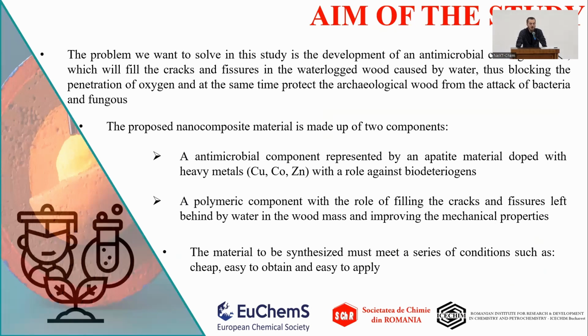In this scope, the problem we want to solve in this study is the development of an antimicrobial material which will fill the cracks and fissures in the waterlogged wood caused by water, thus blocking the penetration of oxygen and at the same time protecting the archaeological wood from the attack of bacteria and fungus. The proposed nanocomposite material is made up of two components: an antimicrobial component represented by an apatitic material doped with heavy metal, with a role against biodeteriogens, and a polymeric compound with the role of filling the cracks and fissures left behind by water in the wood mass and improving the mechanical properties.